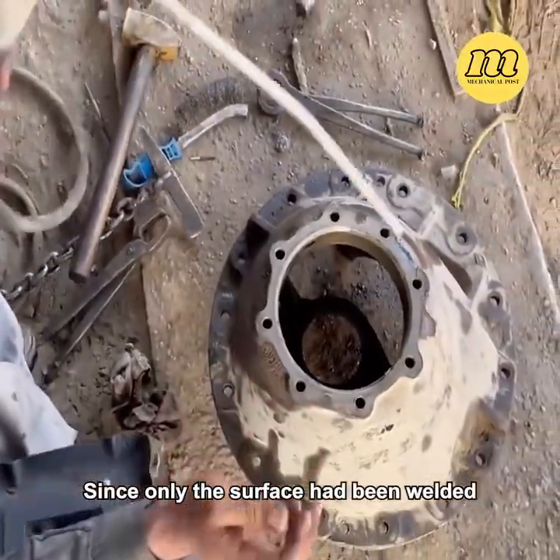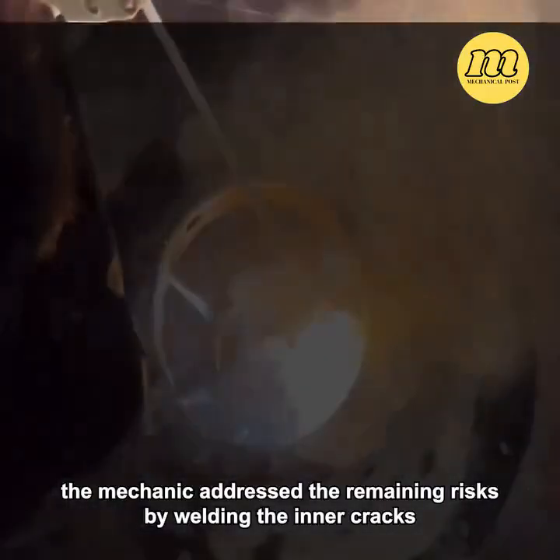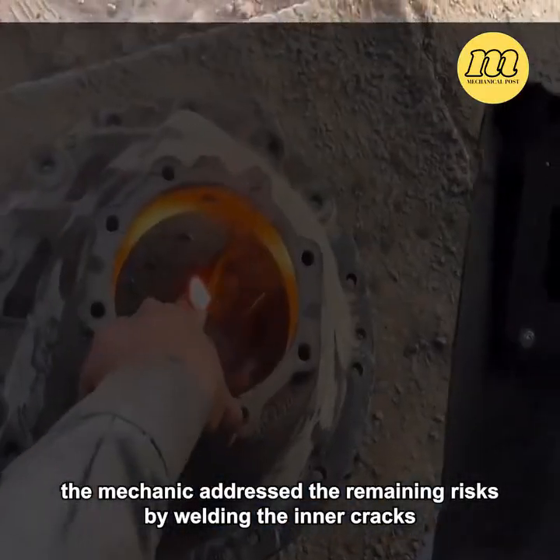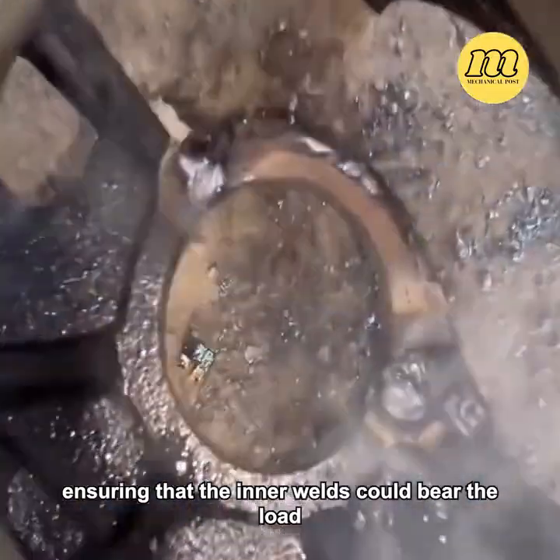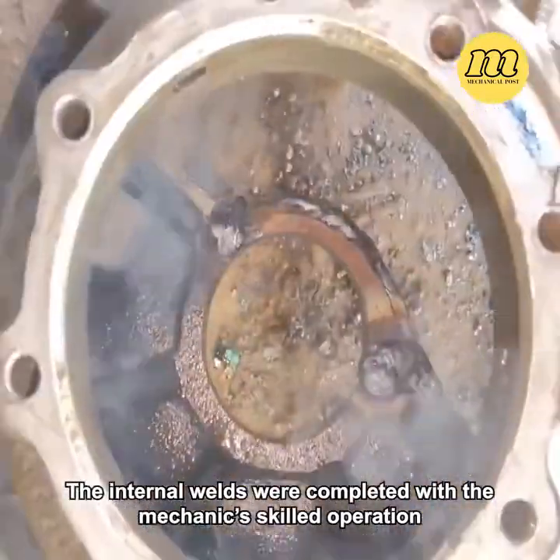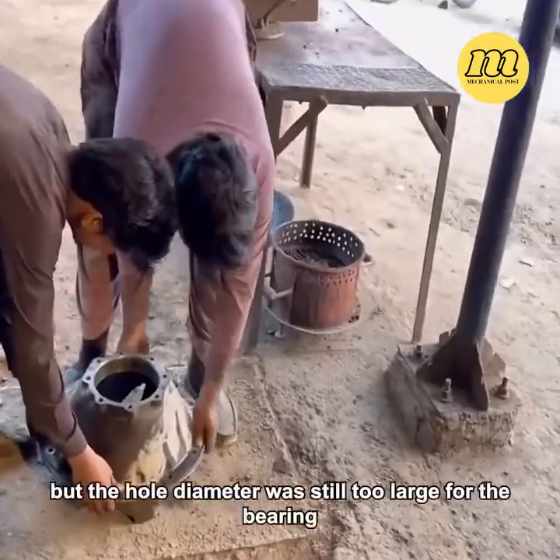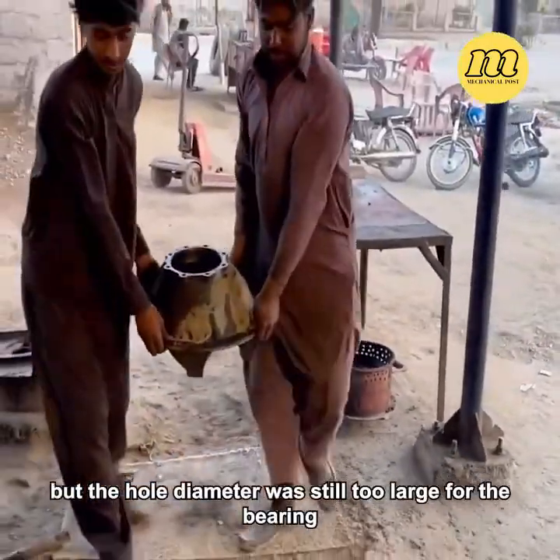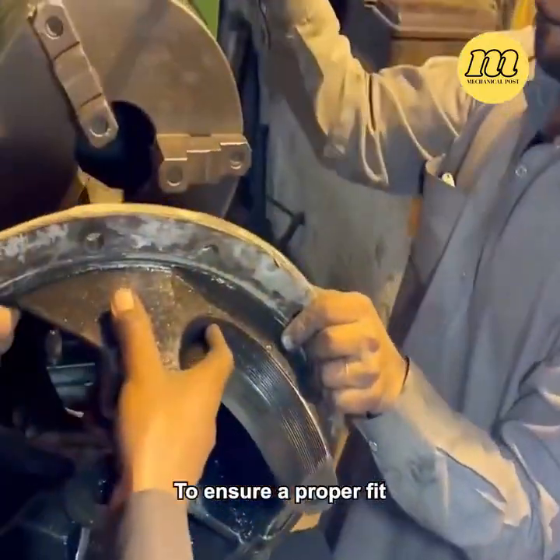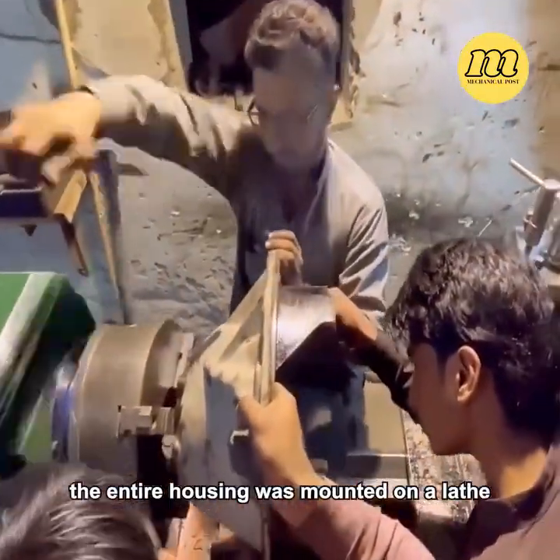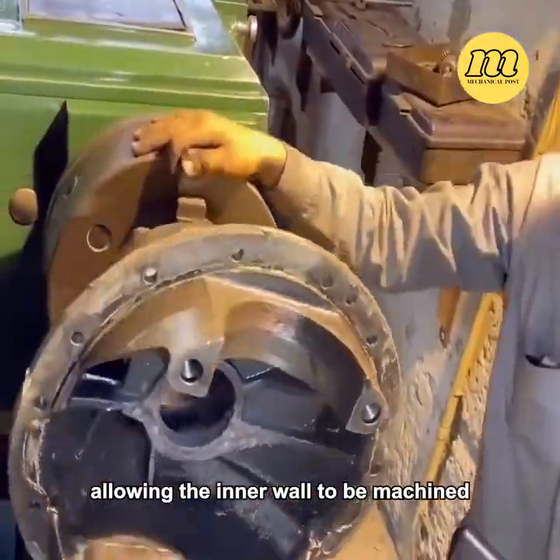Since only the surface had been welded, the mechanic addressed the remaining risks by welding the inner cracks, ensuring that the inner welds could bear the load. The internal welds were completed with the mechanic's skilled operation, but the hole diameter was still too large for the bearing. To ensure a proper fit, the entire housing was mounted on a lathe, allowing the inner wall to be machined.